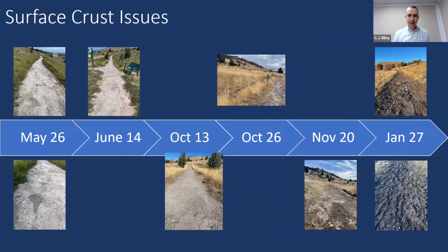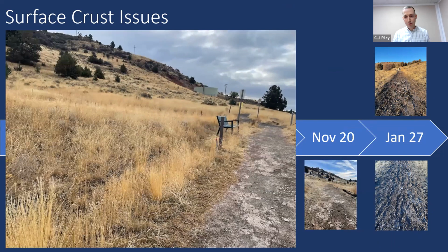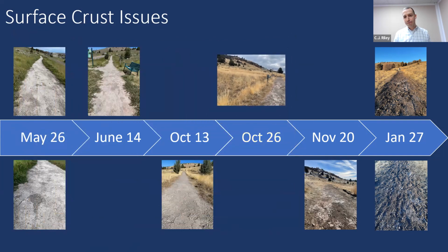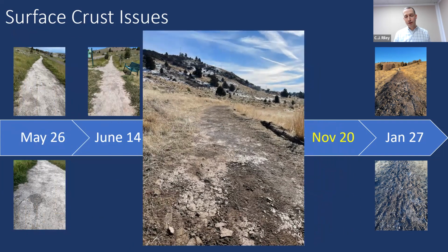And you can see now at the start of that trail, getting later into the year, we do have more degradation of that surface. So as well as some of this material was bound in spots, it's simply not strong enough to stand up to foot traffic, wheeled vehicles, and that sort of thing. Getting into the winter, after some snows, some freeze-thaw, which is detrimental to pavements of any kind, we've got further deterioration. You can start to see some of the native soils appearing where the trail surface has really broken down.